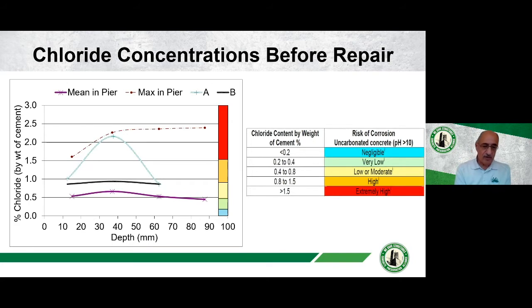So we took out all that concrete, but there was no attempt really to remove all the chloride contaminated concrete, and that's what you would normally expect. We just took it out to clean steel and embedded the anodes.